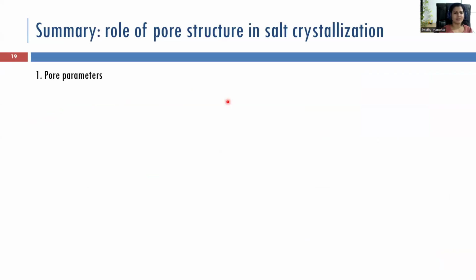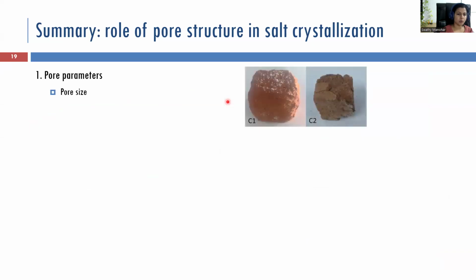Summarizing all that I have talked so far, the parameters influencing the material's salt crystallization resistance are divided into two: pore size and connectivity. In pore size, recall C1 and C2 were the samples representing larger pore and smaller pores.